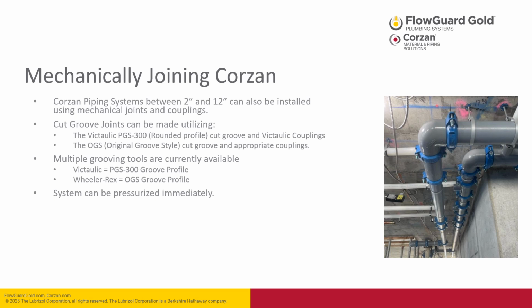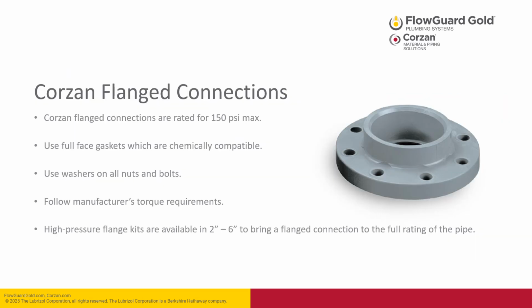When using mechanical joints, the system can be pressurized immediately. Corzan can also be joined using flanged connections. Corzan flanged connections are rated for 150 psi maximum. Use full face gaskets, which are chemically compatible with the Corzan material. Use washers on all nuts and bolts, and follow the manufacturer's torque requirements. If needed, high-pressure flange kits are available from 2-inch to 6-inch to bring a flanged connection up to the full rating of the pipe.